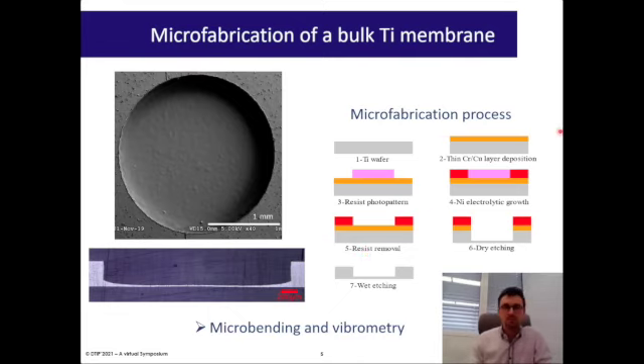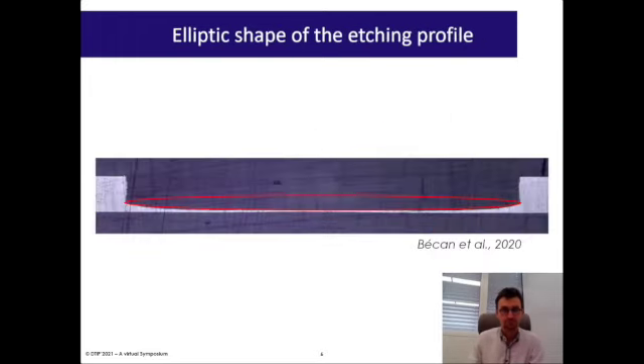The obtained membranes were characterized by microbending and by vibrometry. If we take a closer look at the membrane, we can see that the membrane is not of uniform thickness, but it can be modeled by an elliptic shape. This model was already used for previous results obtained for bulk testing with lots of success.